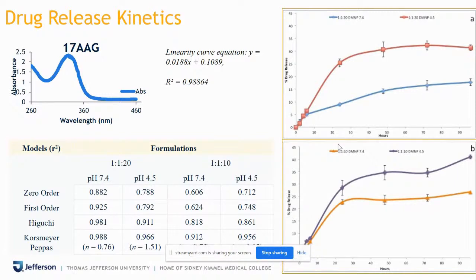Further, we also mapped these release kinetics with some standard models in the world of drug kinetics, like zero order, first order, and Higuchi, which is in the table I've shown here. The data points were mapped for these release kinetic models. What we found was that Higuchi and Korsmeyer-Peppas had really high R squares in both acidic as well as neutral pH conditions for both the formulations. So we think that it follows Fick's law of diffusion and polymer erosion for the release of the drug.